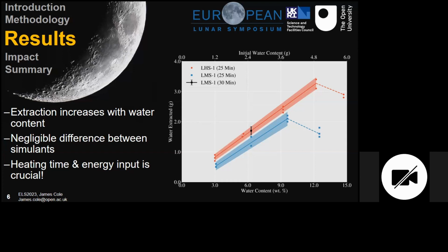So what I did to show this was I did a 30-minute run, and I just did an input energy calculation. What this showed was that this black data point lies perfectly on the Highland simulant line. So what I'm trying to show here is that the simulant composition doesn't really have that much effect on extraction, which is quite surprising given what happens at the higher temperatures. And so what it indicates is that a microwave payload on the lunar surface, especially in these PSRs, wouldn't need to be as careful with what the composition would be.